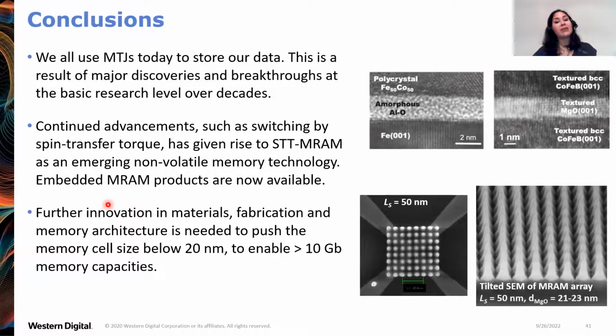We continue to make advancements, such as the discovery of spin transfer torque that allows us to switch magnetization without needing a magnetic field. And this has given rise to emerging non-volatile memory technology, which is spin transfer torque MRAM, and there are products of this available now. So to push this technology even further to a high density STT MRAM, we need further innovation in materials and fabrication and memory architecture to push the cell sizes to 20 nanometers and below with very good performance.